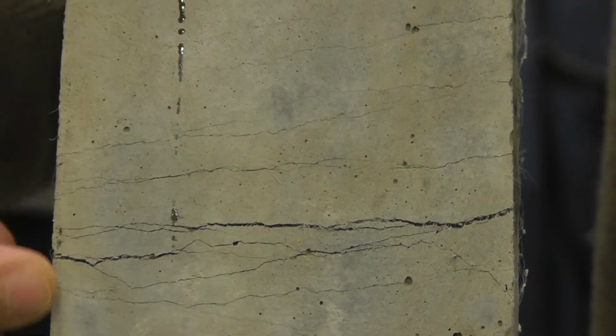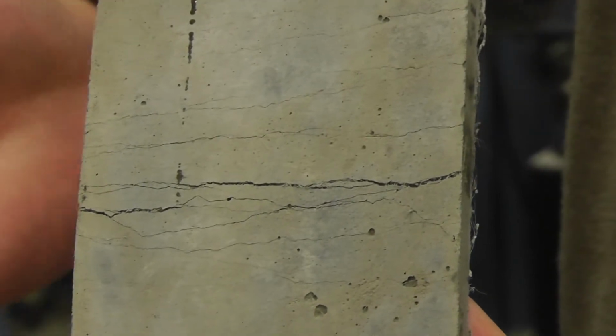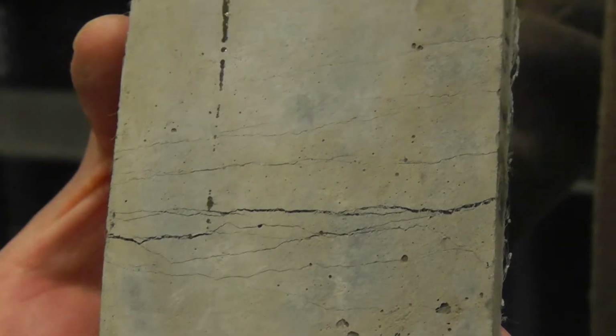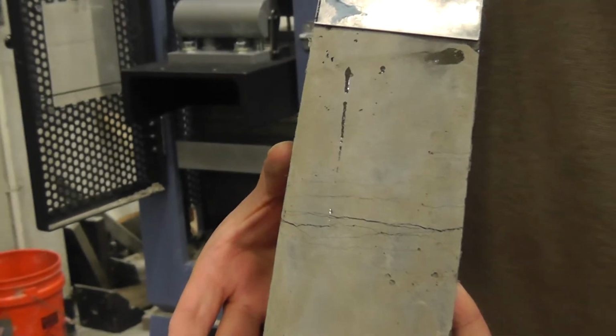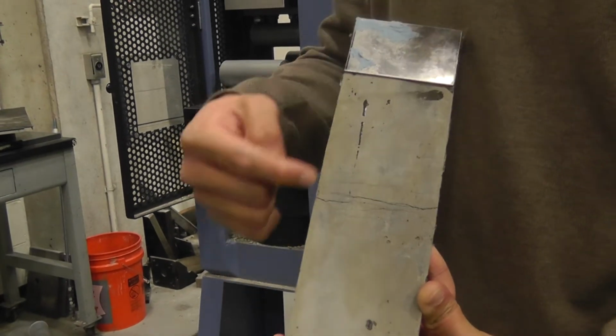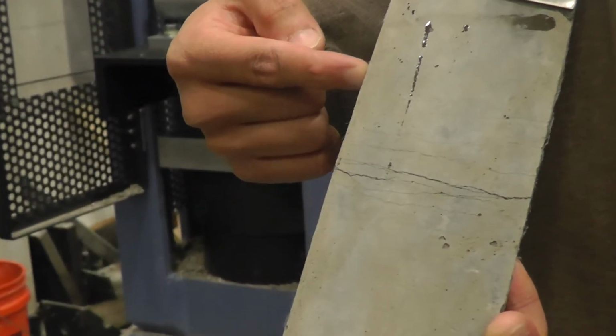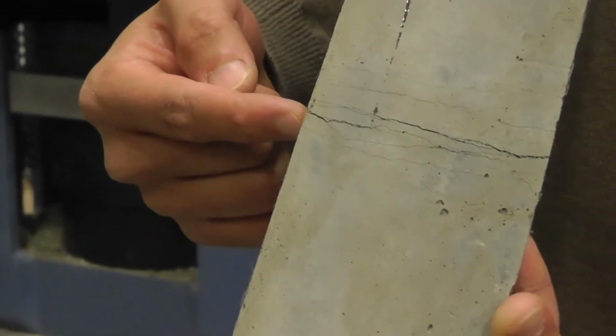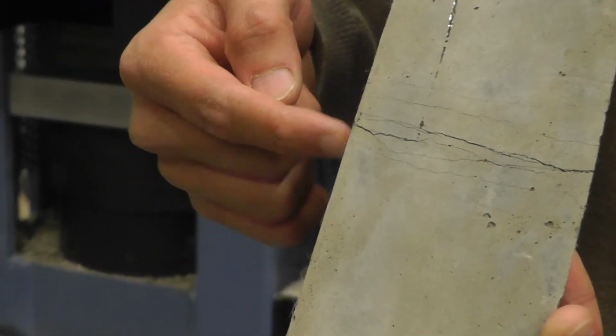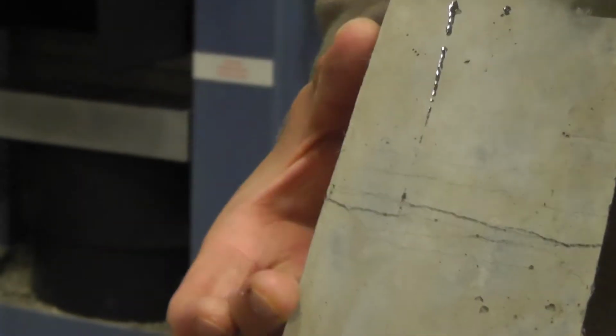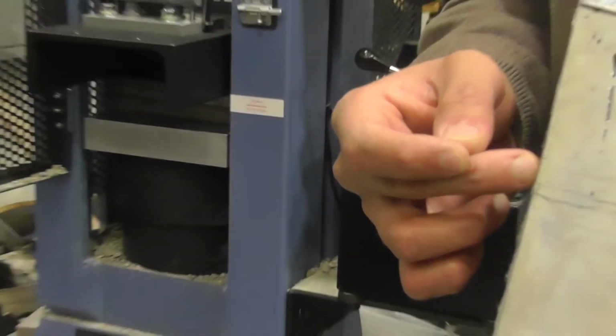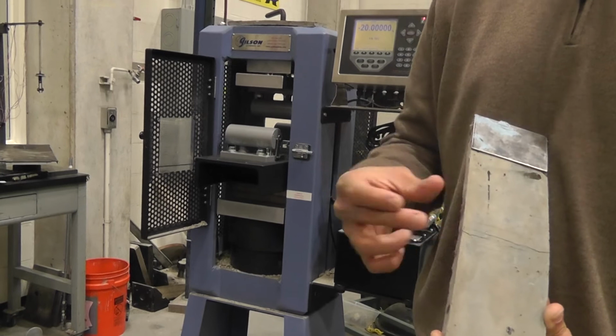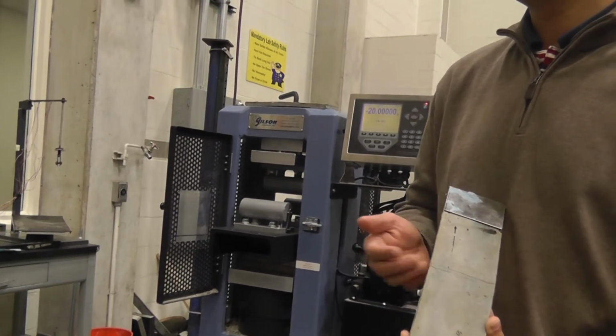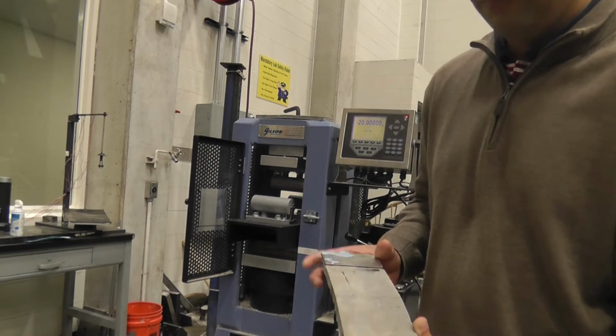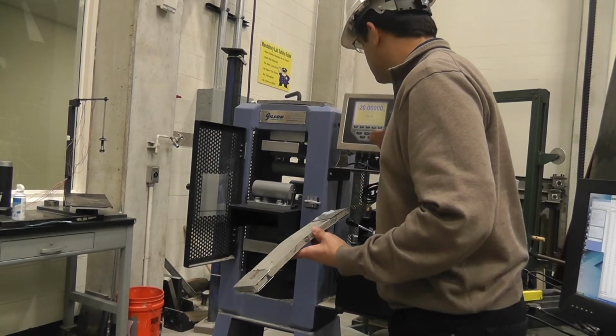So you can see all these multiple cracks over here at the bottom of the plate. Okay. So if we did the 4-point bending test, the rollers would have been somewhere over here, so you would have seen such saturated cracking all the way from here to here. But here it's a center point loading, so the maximum bending moment is at the center. But even though you are seeing the damage spread, in spite of this concentrated load. So that is the special quality of these ductile concretes. They can spread the damage because of the material's tensile ductility.